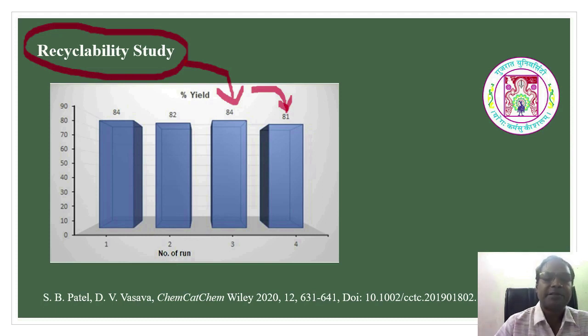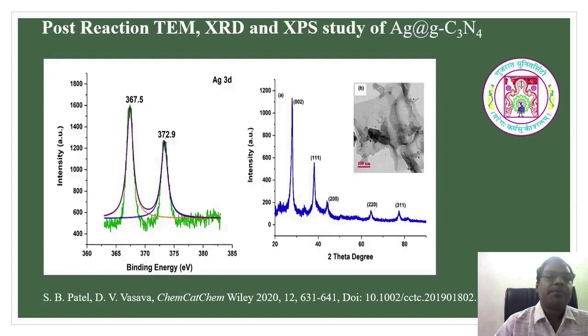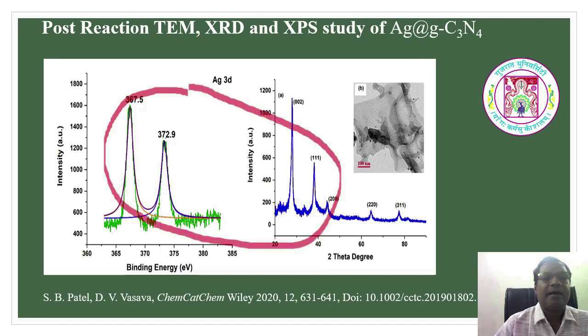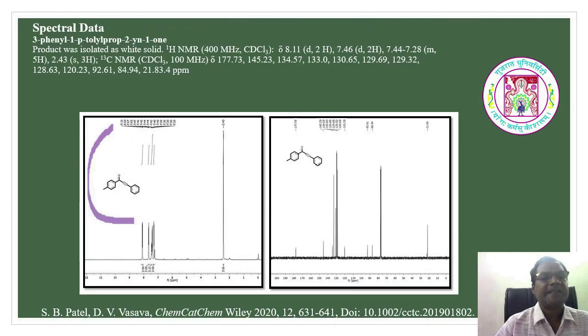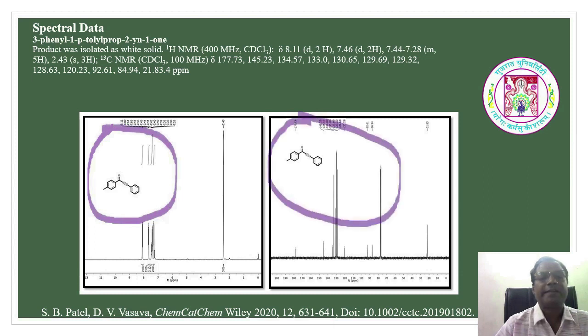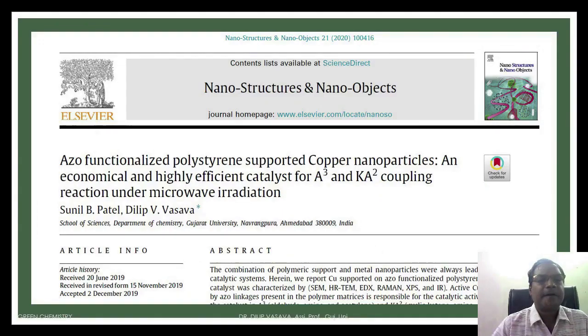Not only that, the same reaction was carried out on the gram scale. The 78% yield is reported with the catalyst, and the post reaction TEM, XRD and XPS studies also. The synthesized Ynone is confirmed by the 1H NMR as well as the mass spectra.